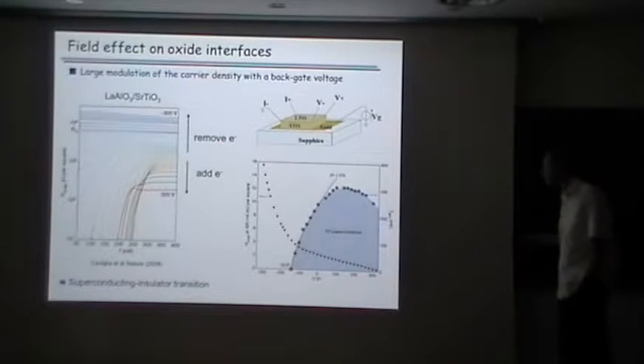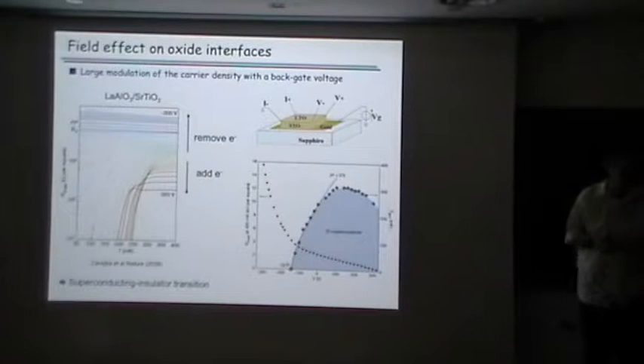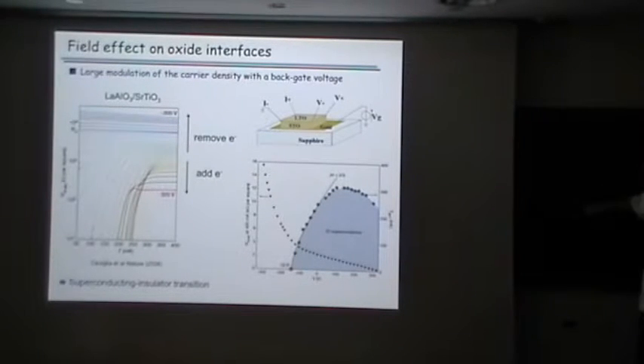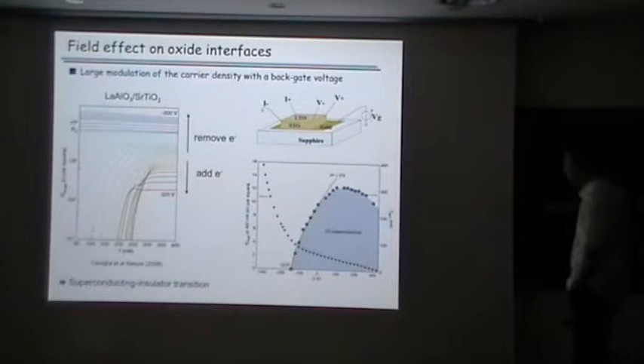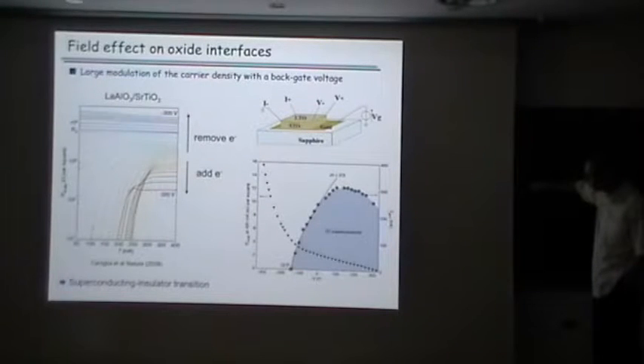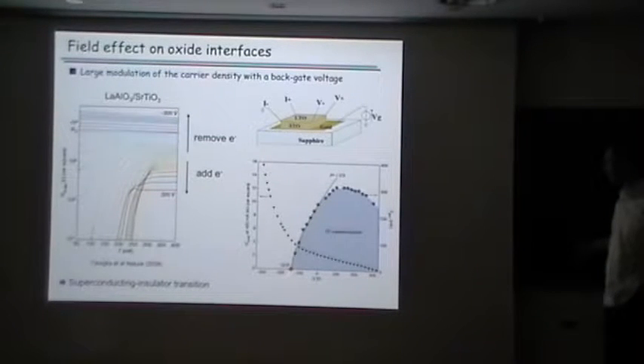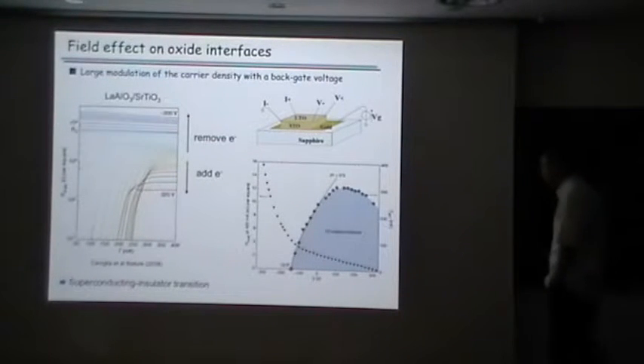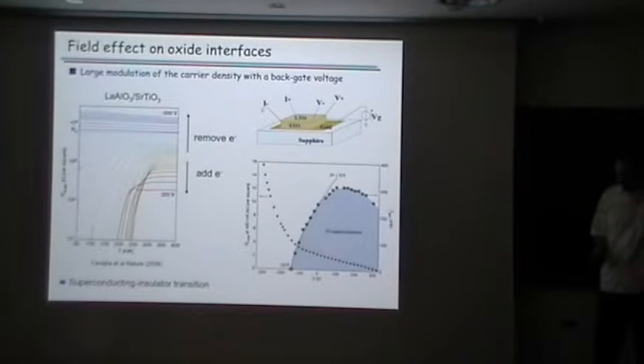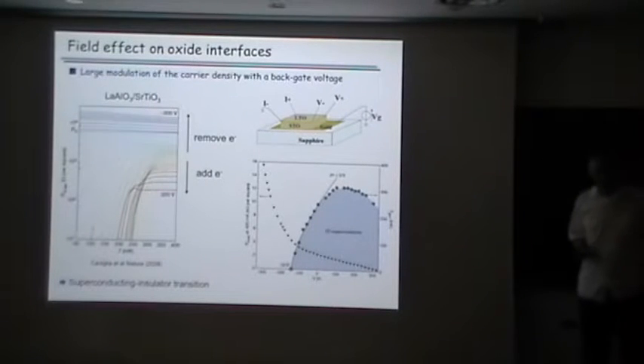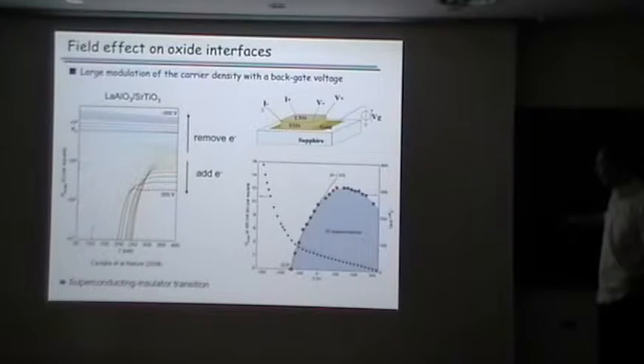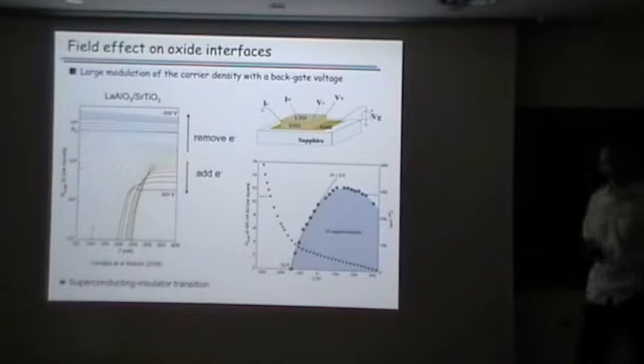The maximum is around 300 milli-K, which again is the Tc of strontium titanate. So it's the same kind of dome you can see just with strontium titanate. The resistance has this monotonic decrease with some kink here. So they claim that here there is a quantum critical point, and that when you change the voltage, the number of carriers, you cross this point. And they make an analysis with a kind of funny exponent.